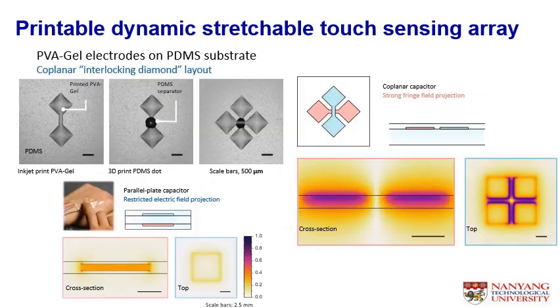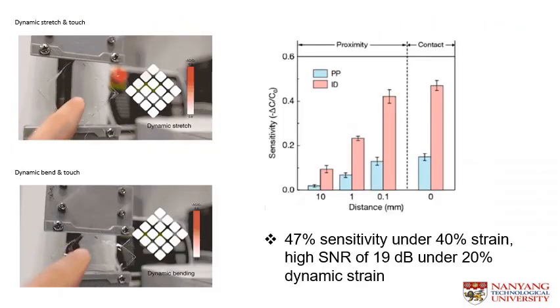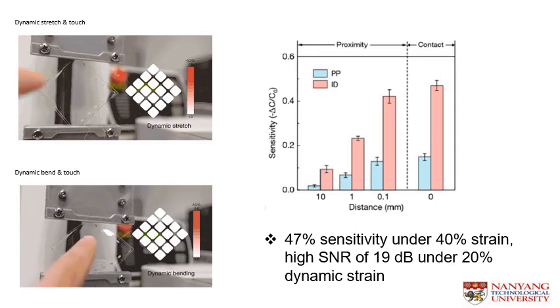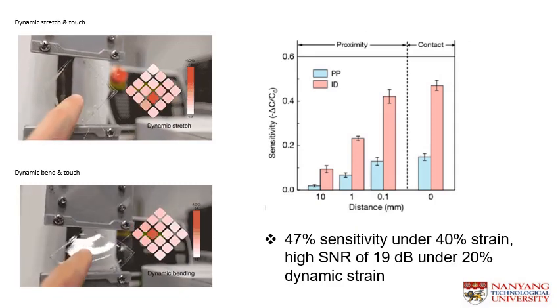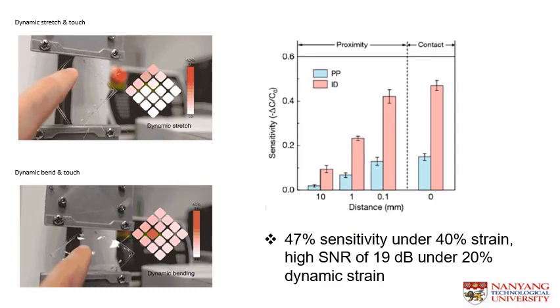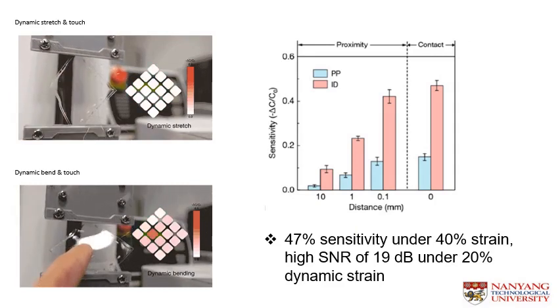As we can see here, the gel that comprised of PVA with salt and water allow us to make interlock diamond layout with a separator curated by a 3D printable PDMS. The coplanar structure enhances the fringing field projection and therefore improves the sensitivity of the touch sensing array. As demonstrated here, in the dynamic stretch and touch and dynamic bend and touch, the touch panel is functioning well.